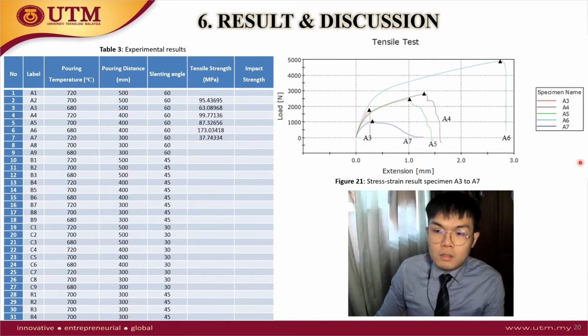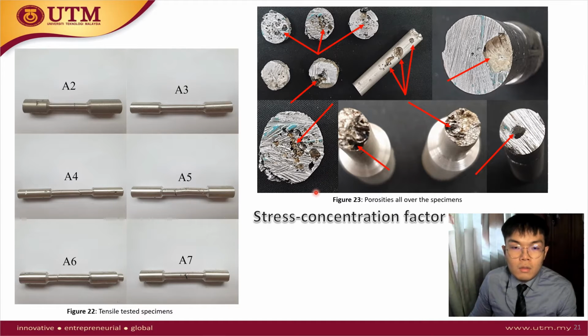You can see the result is fluctuating in the stress strain graph. The fluctuation of the results is contributed by the casting defects, which act as stress concentration factors. You can see porosities appear randomly all over the specimens, which produces inaccurate results.